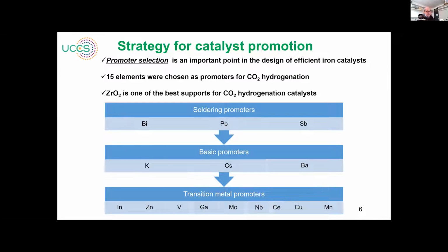And these were supported catalysts, which means that nanoparticles of iron and also promoters were dispersed on a porous support. If we see the literature for CO2 hydrogenation, zirconium dioxide is one of the best supports because it has relatively high basicity and low hydrophilicity. If you have a very hydrophilic support, for example alumina, and we produce a lot of water during the reaction, the support can be damaged after running the reaction for a long time.